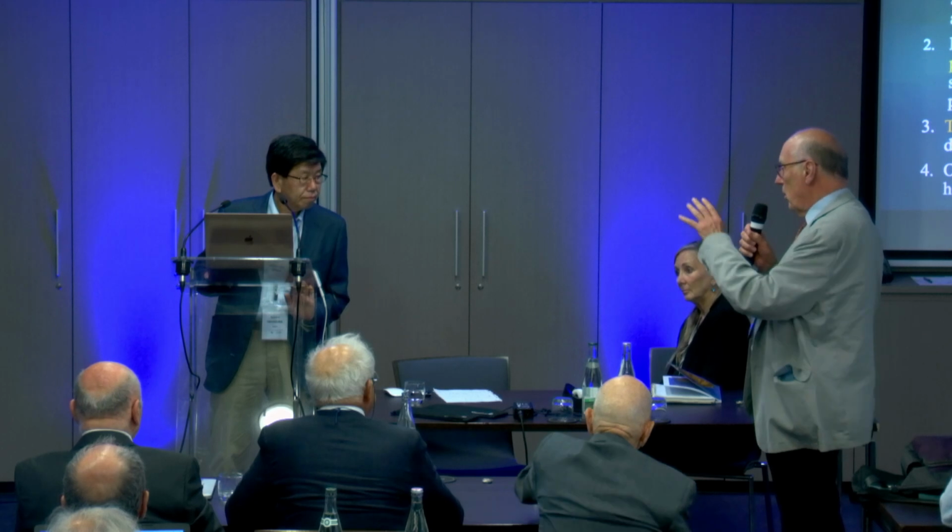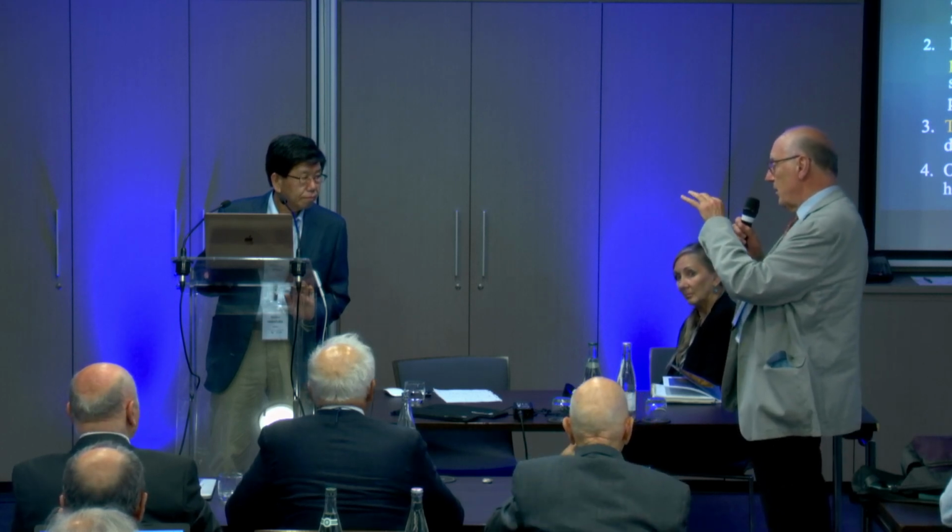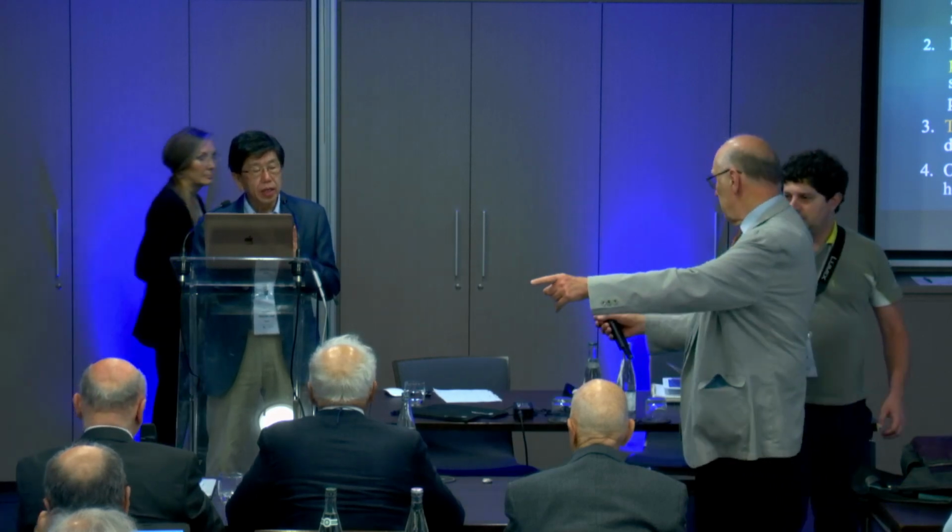You said you used two-color surface temperature measurements. Is it sufficient to be sure all these measurements are not an artifact of emissivity? Yes, this is very important. Emissivity, of course, changes. But if we use the two-color method, usually it is okay, under the assumption of gray body radiation, as Professor Kasagi says. So usually the two-color measurement is correct for the measurement.